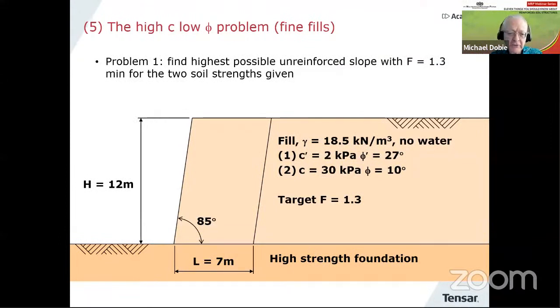So here's the problem: a 12-meter high structure, 85 degrees. The first problem is to find the highest possible unreinforced soil slope with a safety factor of 1.3 for the two soil strength values given there, the 1 and the 2 which I mentioned earlier on. What you would do is put that into a slope stability program, and you basically move the circles further and further down the facing until you start to get a safety factor less than 1.3. So what are those heights? Well, for the C' and phi' values, it's just 0.5 of a meter, and then you start to get failures.